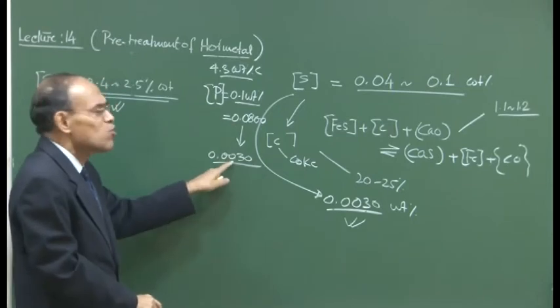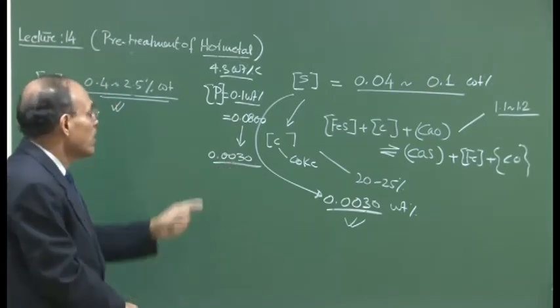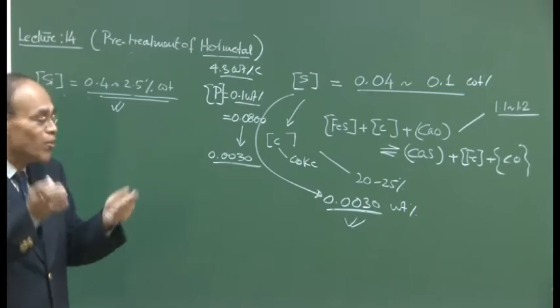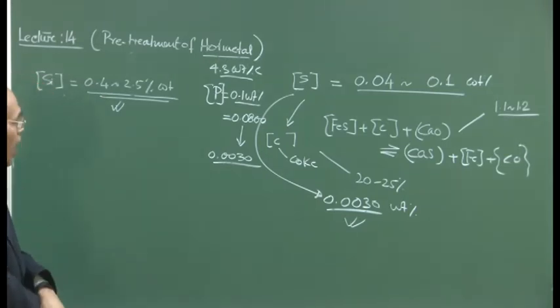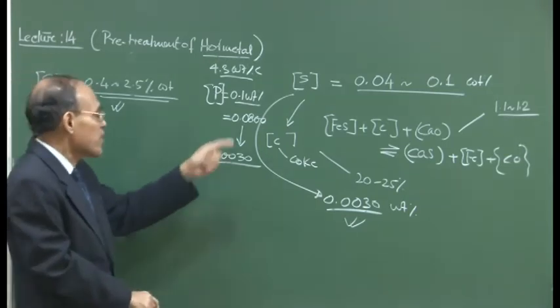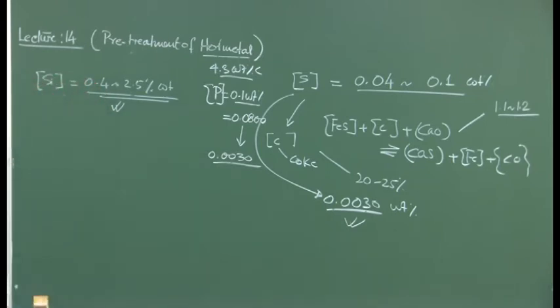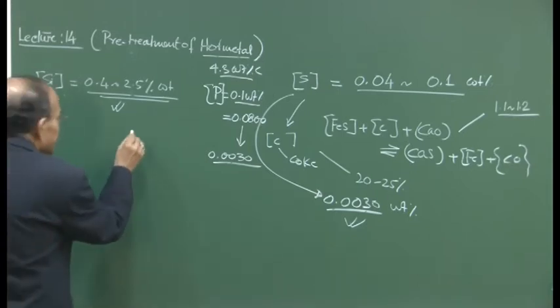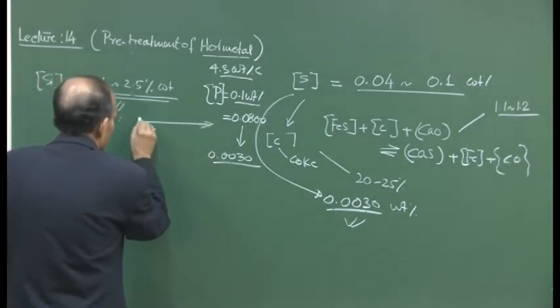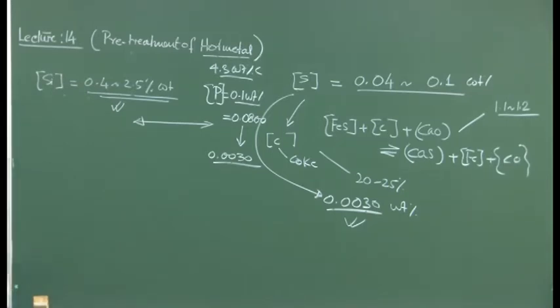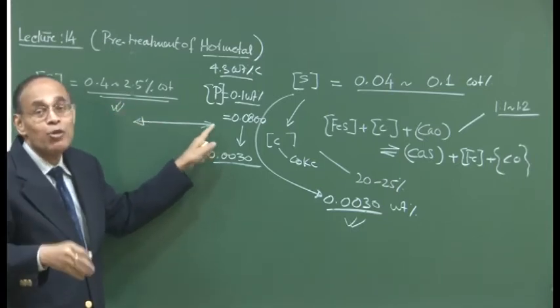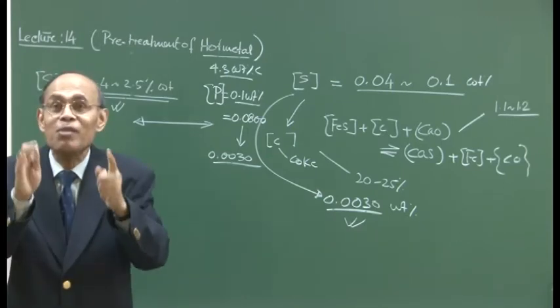And this poses no problem, except that phosphorus elimination will require a basic condition, as we will see. So lime addition will have to be there. So the phosphorus elimination happens at the expense of the cost of lime. We must understand that there is an indirect relationship between silicon content of the hot metal and phosphorus content of the hot metal. If silicon content of the hot metal is too large, then the heat evolved is so large that dephosphorization is not possible, because dephosphorization is an exothermic reaction.